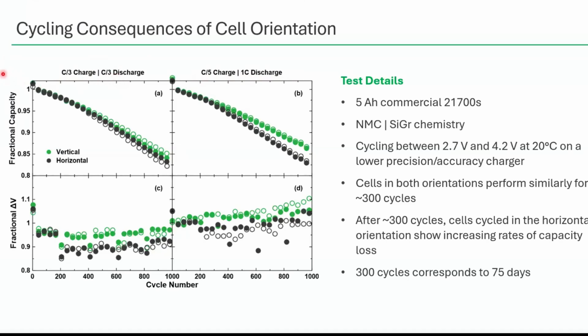Just doing some cycling on a low resolution cycler, we see over hundreds of cycles really no difference between the two. Then during this faster discharge, we start to see some divergence when we do this 1C discharge, and maybe not allow all the electrolyte to get back into the jelly roll during discharge before charging again. Whereas the difference isn't as big in the C/3. So we said, okay, this takes hundreds of cycles to be able to tell, but obviously something fundamental is going on, and probably very early.